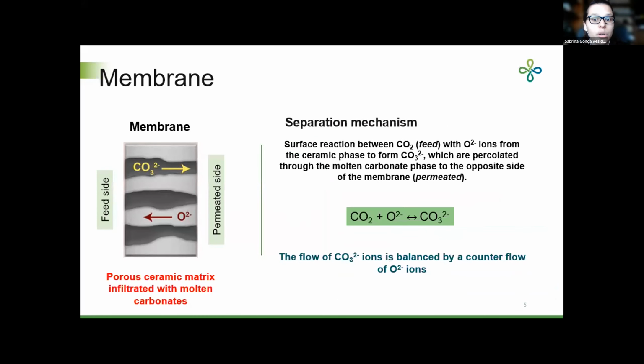So how does the membrane work? The separation mechanism is based on the surface reaction between the CO2 from the feed side and the oxygen ions from the ceramic phase to form the carbonate ion. This carbonate ion is transported through the membrane to the other side, and the reverse reaction occurs, releasing CO2 on the permeate side and the oxygen ions back to the ceramic phase to start the reaction again. So the driving force of this permeation process is the difference of the partial pressure of CO2 on each side of the membrane.